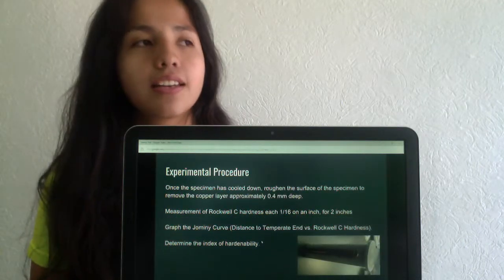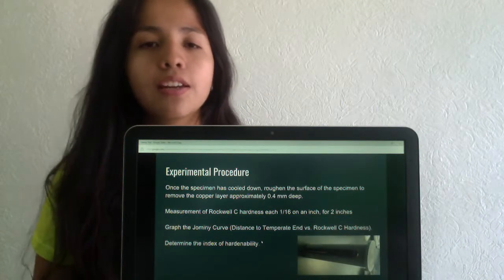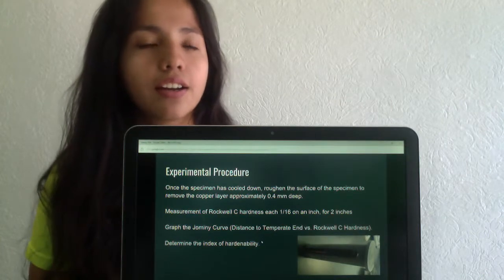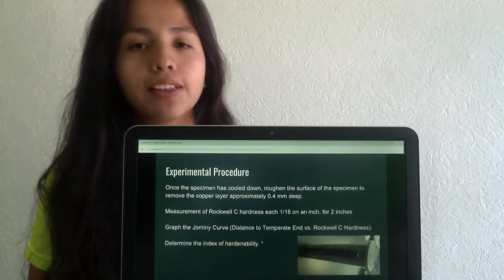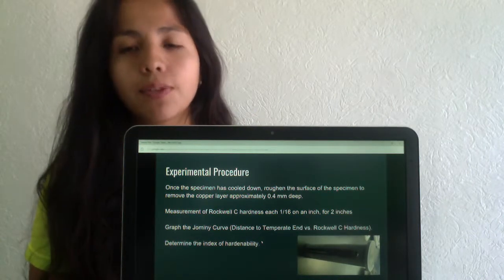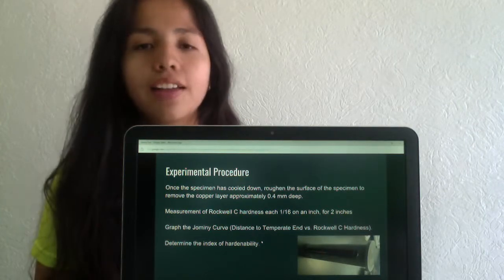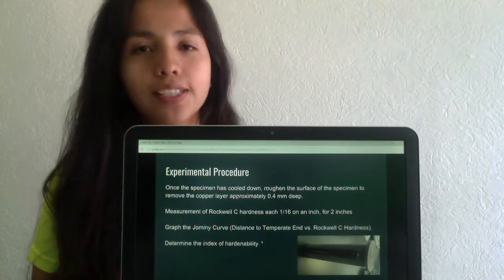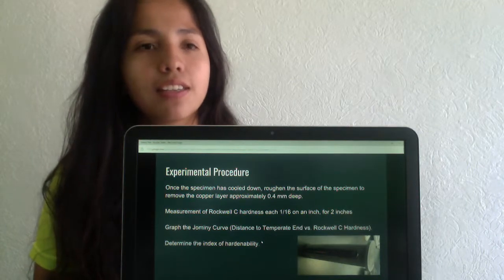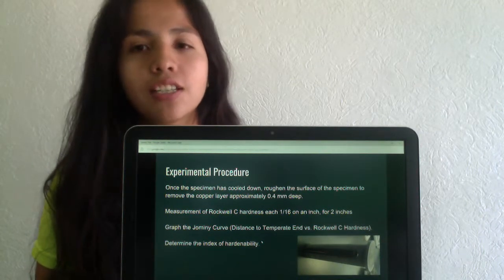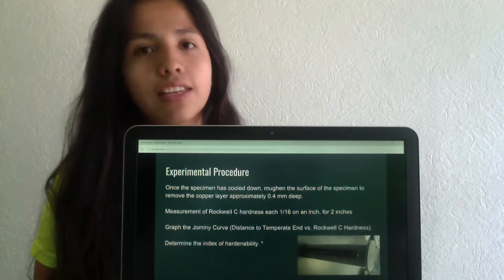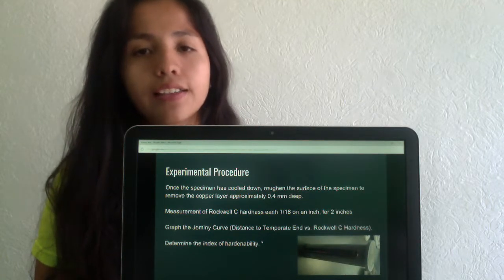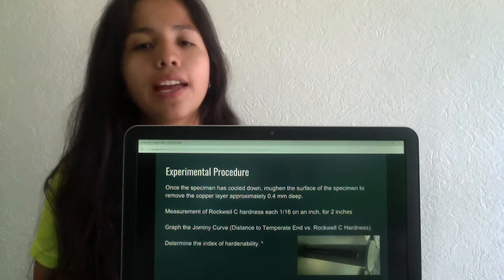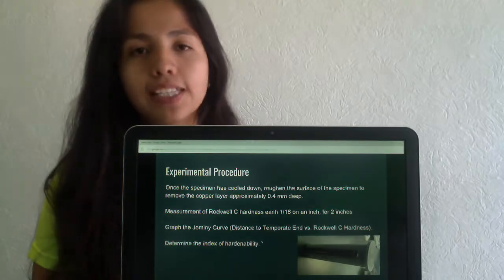Once the specimen is cooled, we remove the copper layer, approximately 0.4 millimeters in depth, and then we measure the Rockwell C hardness for every 16th of an inch in 2 inches, and we graph the Jominy curve and determine the index of hardenability.